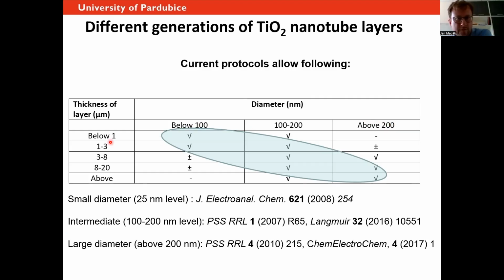So it's pretty broad. If you look at the thickness, there is some dependency on the diameter. So in principle, when you want to grow a low diameter, you have to apply rather a low voltage. And this means that the layers will be rather thin. In contrast, if you apply rather high voltage, most likely you will end up with rather larger diameter and thick layers. So this ellipse shows some kind of optimal region where if you take the recipe, normally even a beginner should be able to reproduce it and make these tubes. The areas outside the ellipse are a little bit more difficult. You need to do some development there and eventually some additional things like cooling of the electrolytes and things like this.